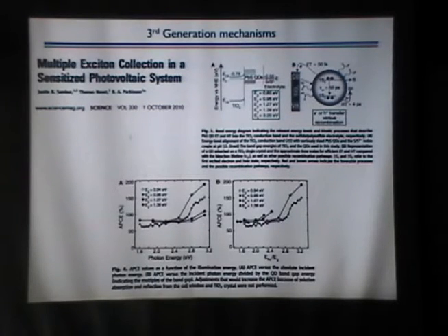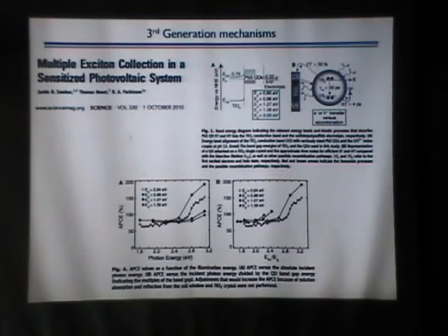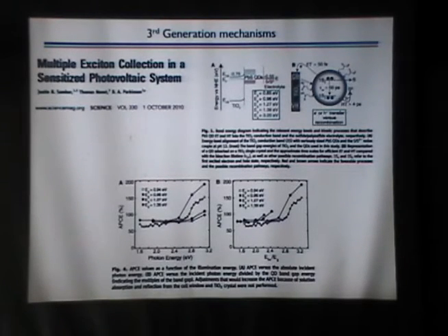What he did was take a single crystal material of TiO2, single crystalline TiO2, and attach to it some lead sulfide quantum dots. So the lead sulfide has a low band gap, I think it's around 0.8 eV, and spectroscopically has been shown to exhibit multiple excitons. This has been shown at NREL, this has been shown at Los Alamos, a couple places. But no one has been able to extract any charges out of those quantum dots, at least above 100% quantum efficiency. So Bruce's group is claiming they have done it.